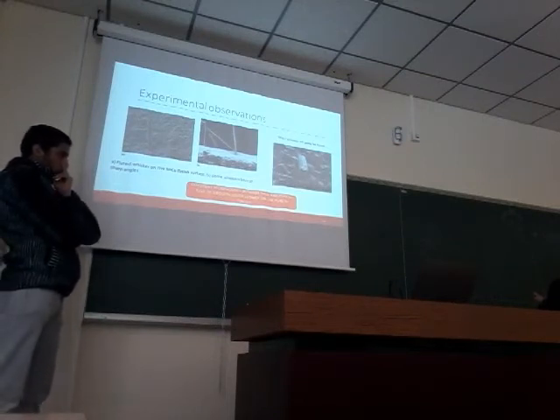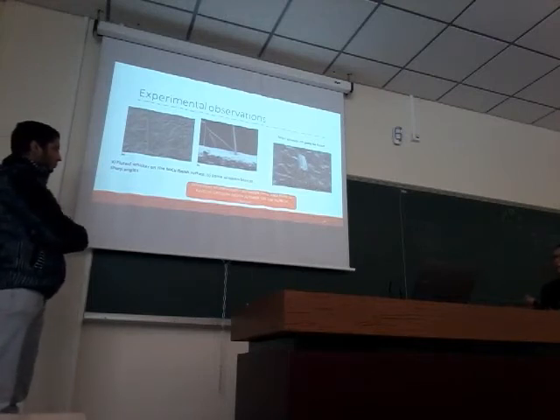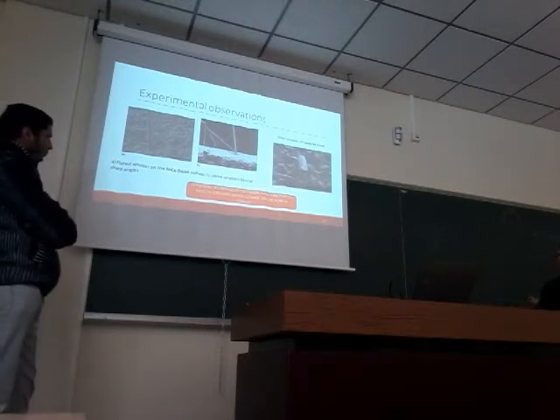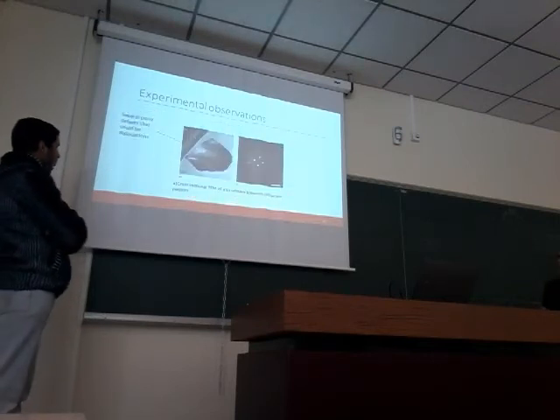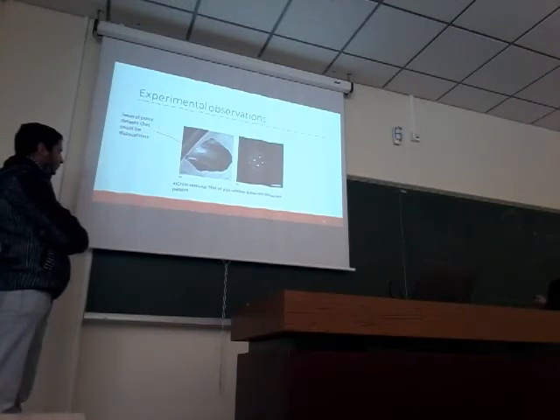So we see that the morphology of the whiskers is very different. Here they are kind of fluted, but here they are more faceted, and here they bend at sharp angles. And we can see that the diameter of the whiskers is about some micrometers, which is very similar to the grain size of the matrix. But the most important remark is that the growth rate of tin copper is faster than the growth rate of tin. And here we have a TEM picture, and we observe some defects that could be dislocations on the whisker.